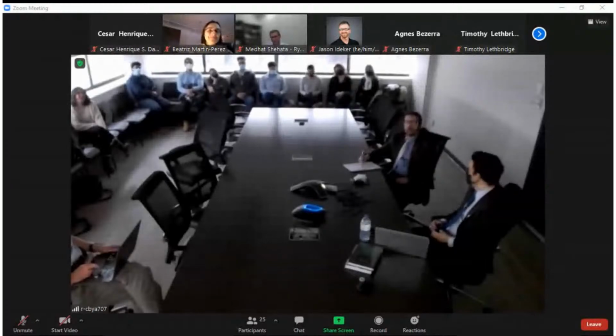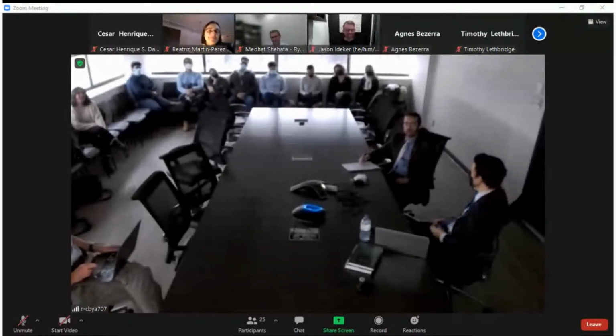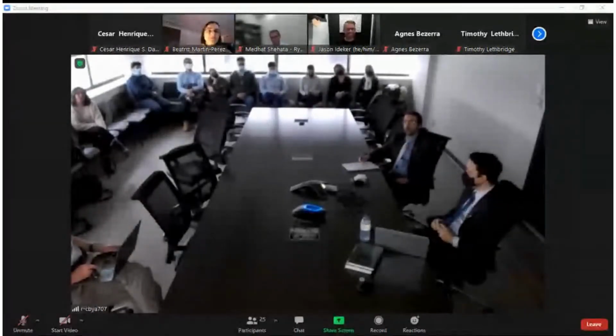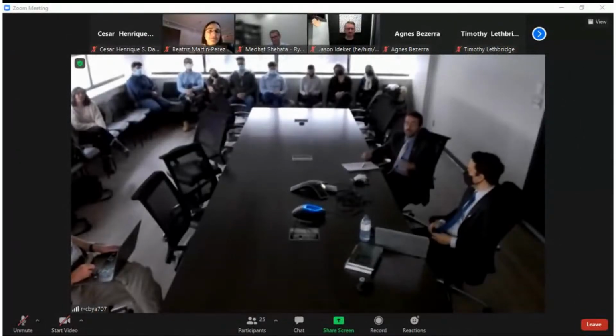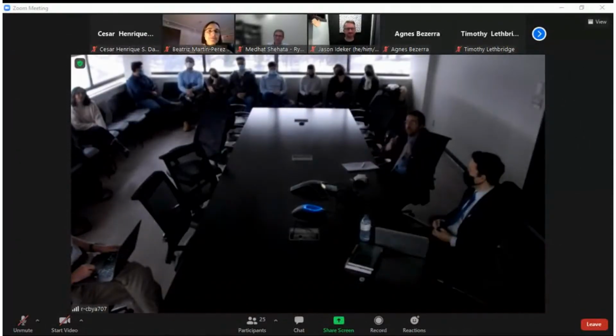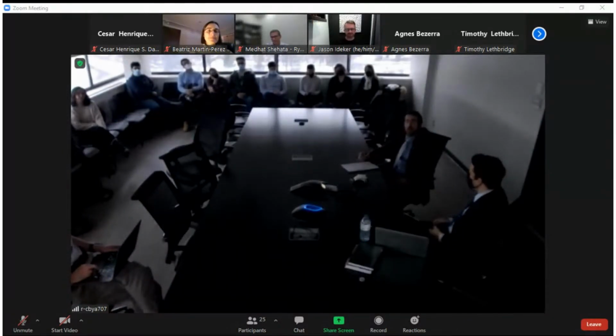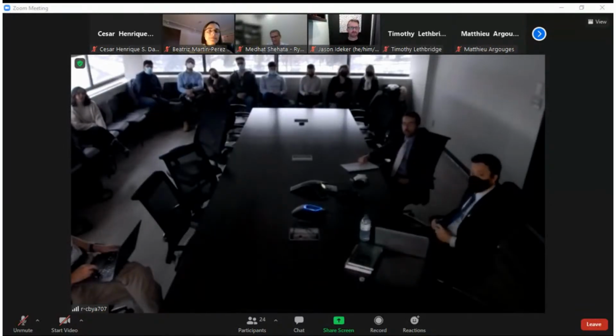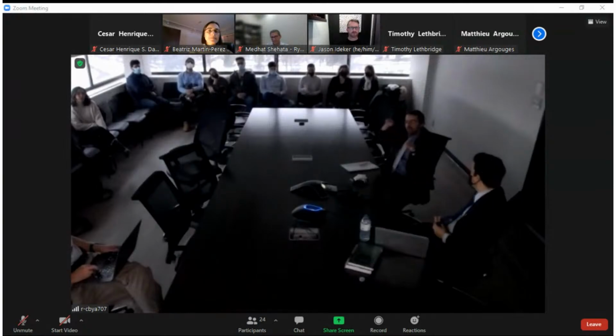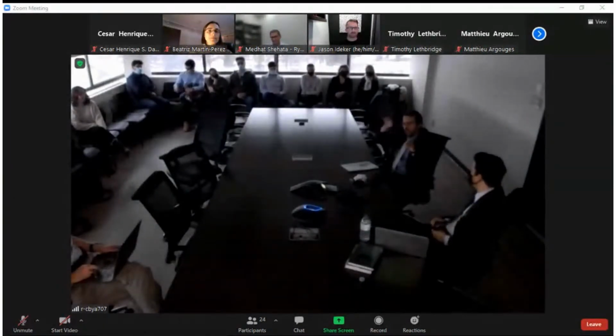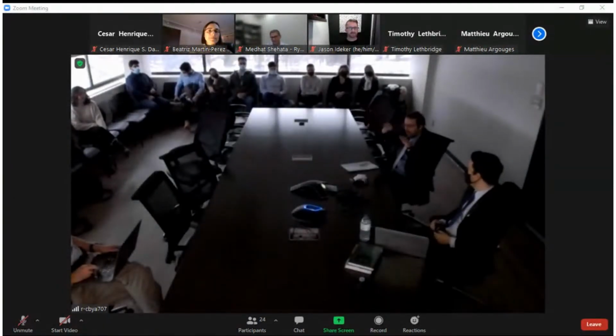Because there is so much variability, especially for deteriorated concrete. For sound concrete it is slightly better. I understand all of the structural engineers that use that from a structural perspective, but regarding deterioration, it's very variable. So then, in my PhD, I did gas pressure tension at McGill. And that was really good, but the problem is that it was diagnostic up until a given point only. Above and beyond 0.10, we couldn't see differences in deterioration.